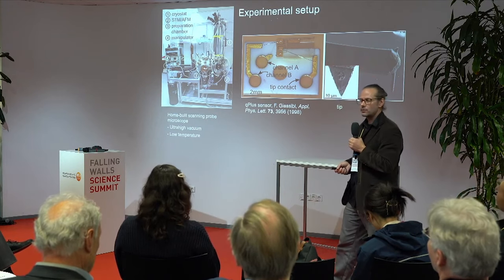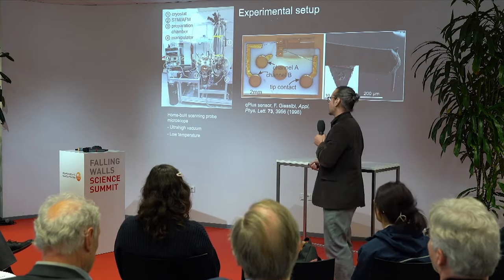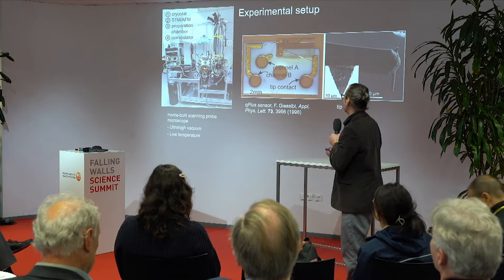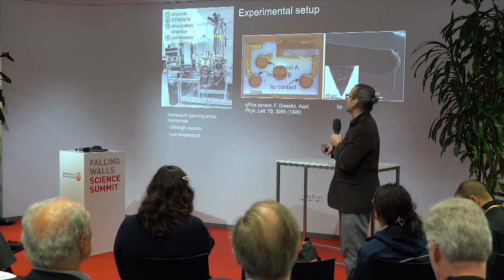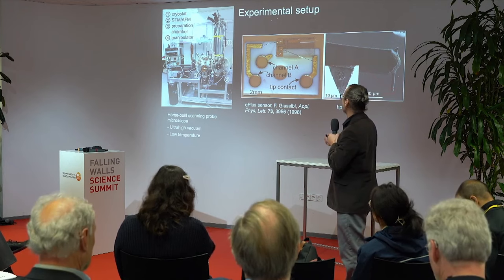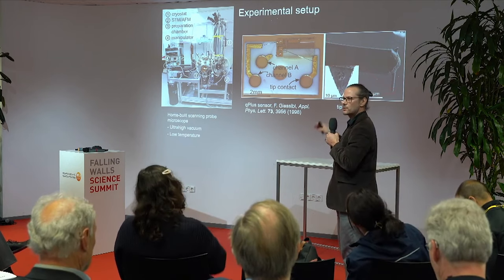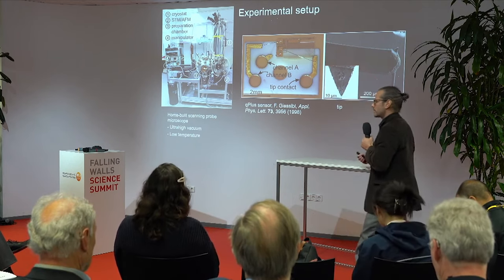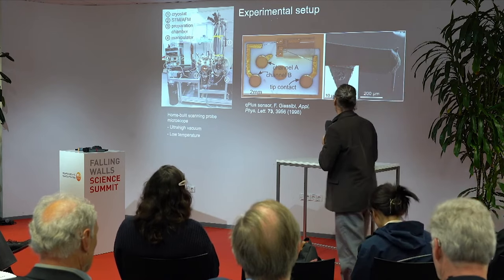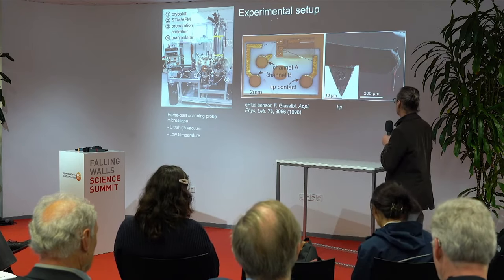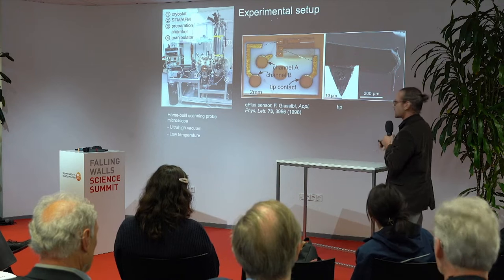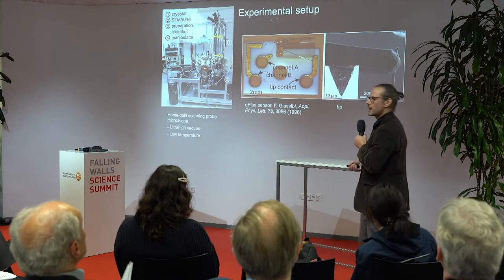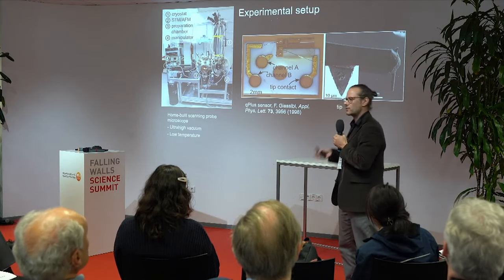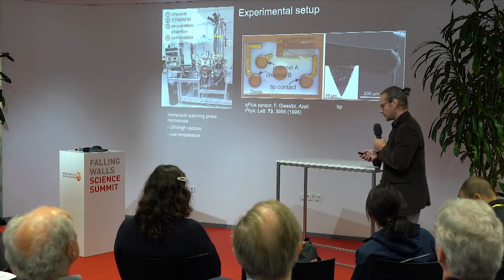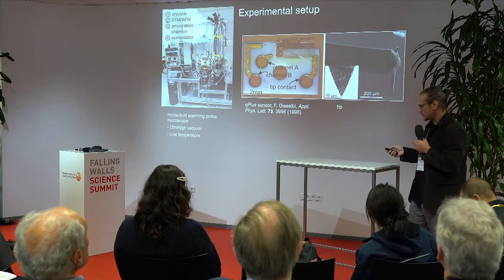It's ultra-high vacuum and low temperature, so we work at 5 Kelvin. In the middle, you see the sensor that we are using. That is the prong of the AFM, and it oscillates with an amplitude of one atomic diameter, one angstrom. And at the end, you have the tip of this microscope. Here you see a focused ion beam image. Then at the end, we pick up this carbon monoxide molecule in the system, and we take these images. OK, that was what we were doing.